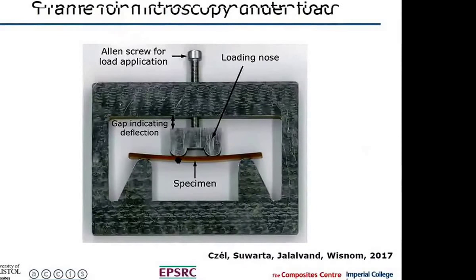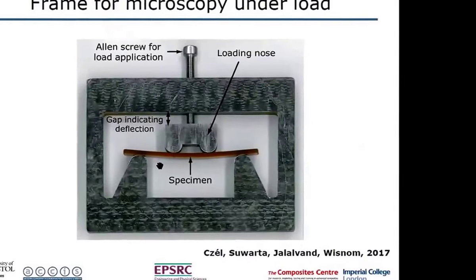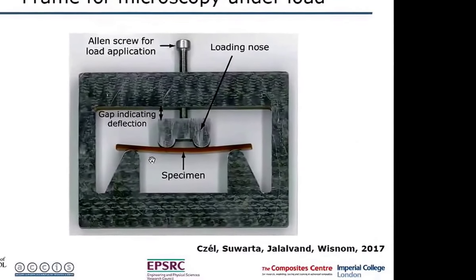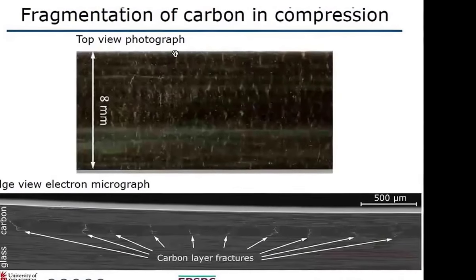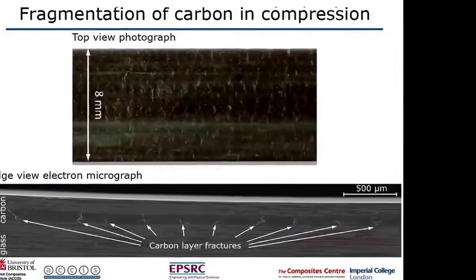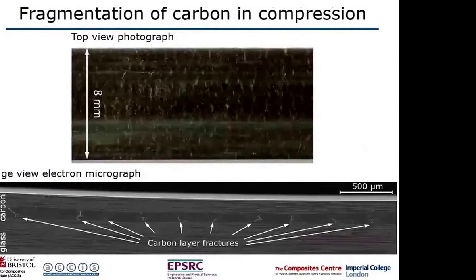Okay, well, we investigated this using a little rig here to enable us to put the thing under load and see what's happening when it's under load. And so we can put this under the microscope to look at the mechanisms, what's actually happening in the fragmentation. So this shows the overall top view. You can see, not quite so clear as in the tension case, but you can see these little flecks here, which are fragmentation and local delamination associated with those fragmentation events in compression.